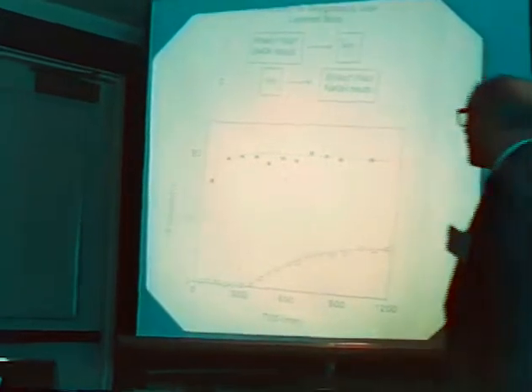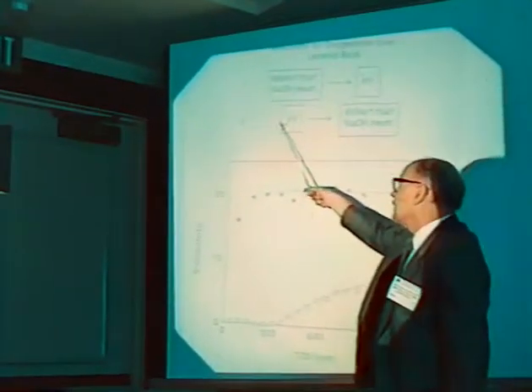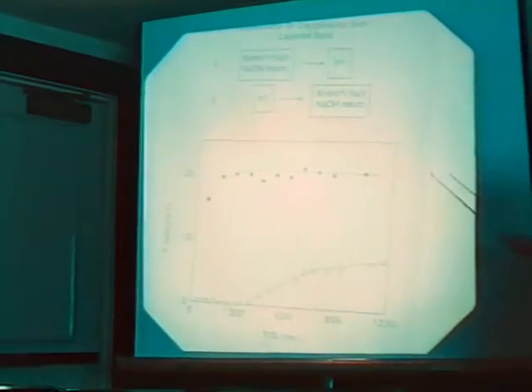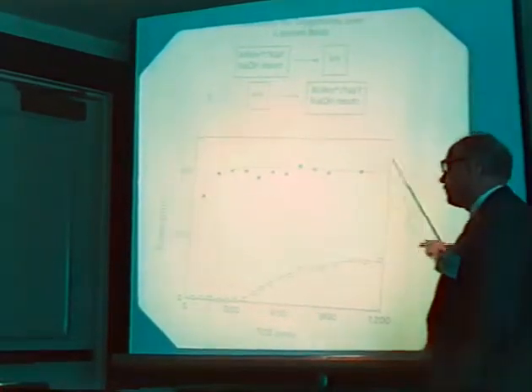We did the control experiment by reversing the order of the two catalyst beds. If the syngas first goes through the HY bed and then through the good catalyst, you get the full glory of your oxygenates. So one conclusion is that protons destroy oxygenates — that is certainly one of the reasons why you must eliminate these protons if you want to make oxygenates. That doesn't prove, however, that this is the only reason — there is still another conceivable hypothesis.